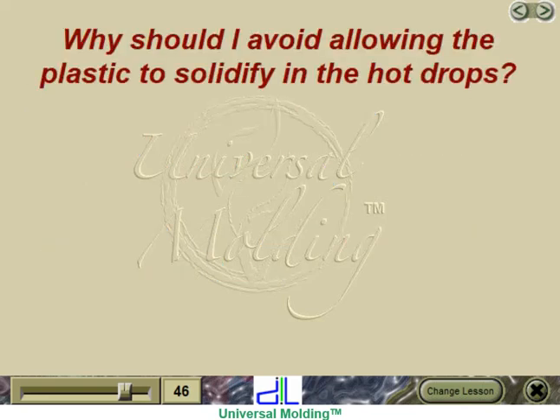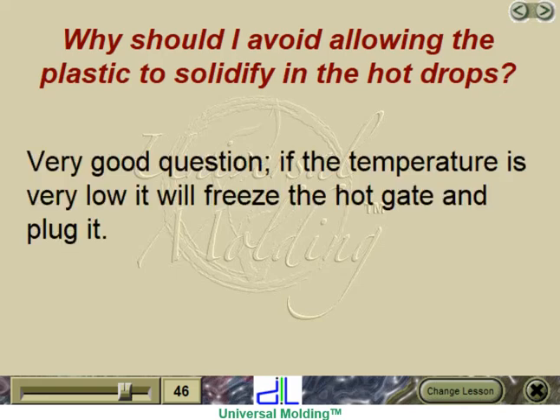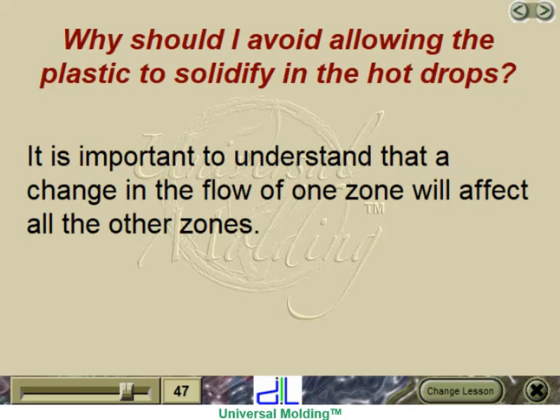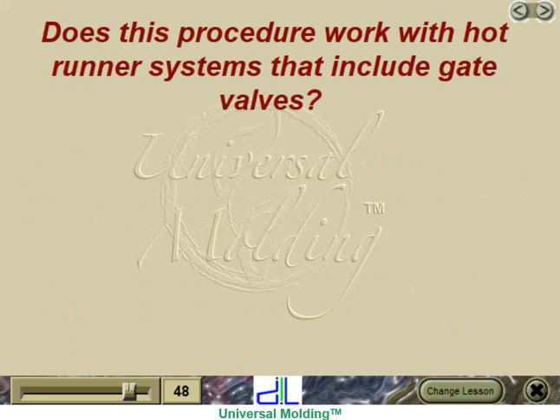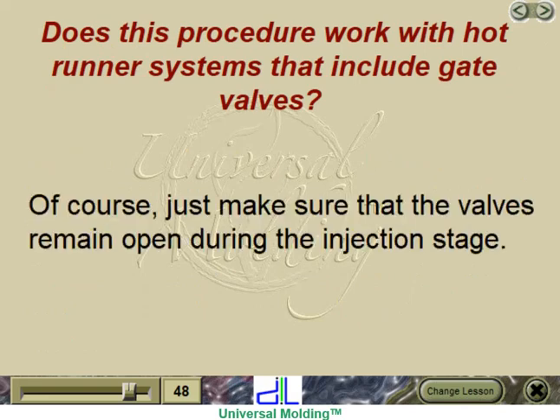Be careful not to cause the plastic to solidify in the drops. If the temperature is very low, it will freeze the hot gate and plug it. It is important to understand that a change in the flow of one zone will affect all the other zones; we recommend making one change at a time and injecting new parts. This procedure also works with hot runner systems that include gate valves — just make sure the valves remain open during the injection stage.